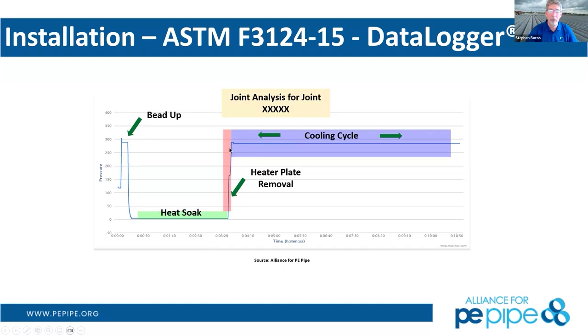This is when that whole joint's being made. You're going to bring it together. You're going to get the rollback beads. And now that joint's done. Now what you have to do, though, is hold that interfacial pressure during the cooling cycle to make sure that it doesn't move or get pulled apart while it's going from that molten phase to the solid phase and then cooling back down to a temperature that you can then take it out of the fusion machine and start moving it around.